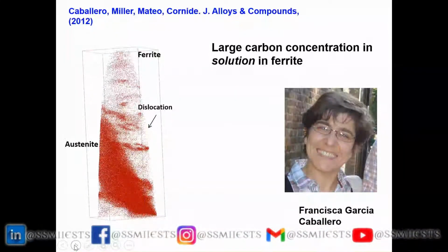to partition. So the idea that occurred to me was, if you introduce carbon in ferrite, then the ferrite will be tetragonal. So we should not think about equilibrium between body-centered cubic ferrite and austenite, but rather equilibrium between tetragonal ferrite and austenite. So I got my colleagues in South Korea to do first principles calculations. And if you go to the next slide, please.